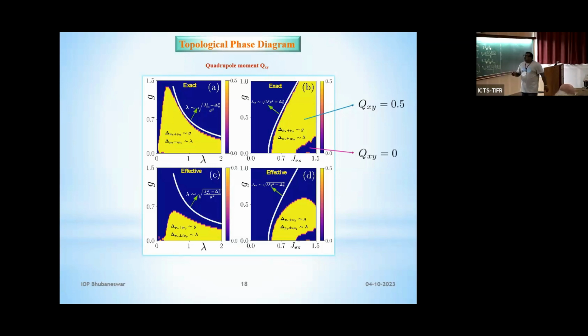And this quadrupole moment, if you see it as a function of the pitch vector and the spin orbit coupling, you will see that this is the topological regime from real space. And this is also from the effective model that I don't have time to go into. But you can see that this is my topological regime. In the topological regime, this quadrupole moment becomes 0.5, and in the trivial regime, it's 0. So this is the characterization of your second order topological phase, which is very different from the first order topological phase.